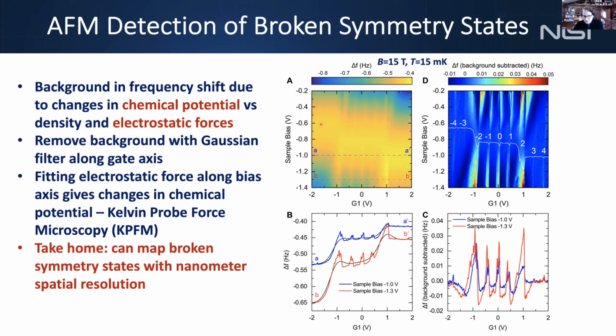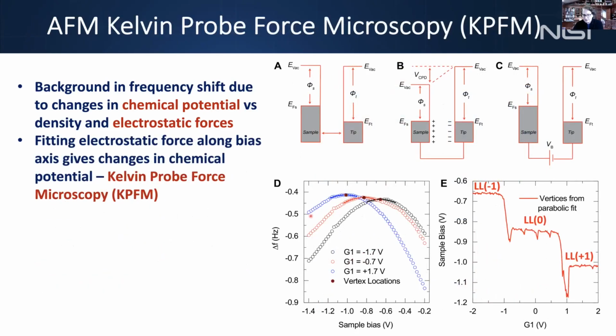And to see that, let's look a little more closely at the background here. So if we just look at the force curves here as a function of bias, you'll see I picked out 3 of them here. This is the standard parabolic response you get for a force curve, but the interesting thing is that this curve is shifting with gate voltage. The peak here, the vertex point, is when the bias balances the contact potential difference, right? So the vertex is the 0 force condition. And the reason why this curve shifts is that when I gate graphene here, I change the work function. So I'm shifting the Fermi level of the graphene when I gate it. And so this parabola is shifting.